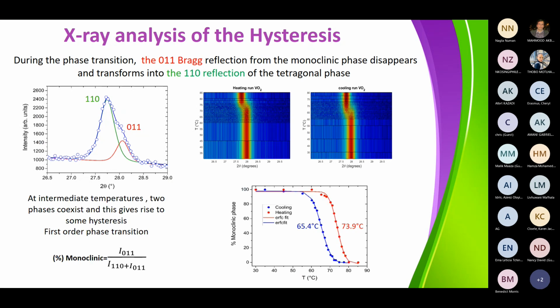And in a first order transition, you have a coexistence of two phases. If you look at the intensity of both reflections by fitting them with a Gaussian function, for instance, you can calculate the percentage of the monoclinic phase as a function of temperature. And that's what we did here. If you heat the film, the transition is occurring at around 74 degrees Celsius, while on cooling, the transition is occurring at 65 degrees Celsius.